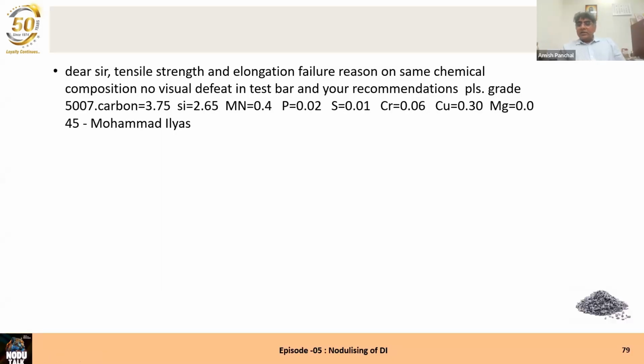He said that, sir, there is a tensile strength and elongation failure on the same chemical composition, with no visual defect in the test bar. What is your recommendation? He has given the chemistry. It is a 500/7 grade. I am looking at your carbon equivalent. It's very high. But sir, his question is that with the same chemistry he is getting a good casting, and with the same chemistry he is having a failure in tensile strength and elongation.